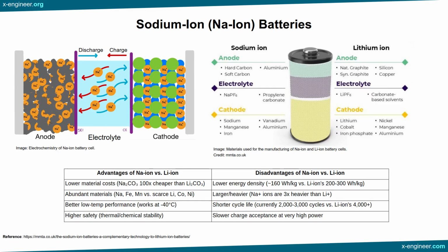Structurally similar to lithium-ion batteries but using sodium ions instead of lithium, this technology presents distinct advantages and trade-offs. While sodium-ion batteries currently offer lower energy density, around 160 watt-hour per kilogram, due to sodium's larger ionic size and mass, they now approach the performance of entry-level LFP batteries, between 120 to 200 watt-hour per kilogram.